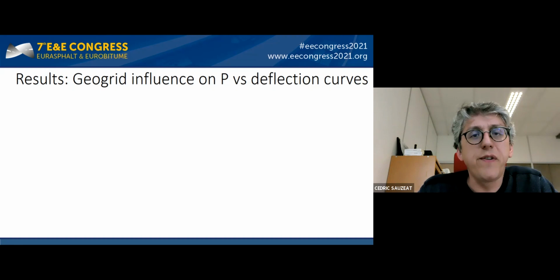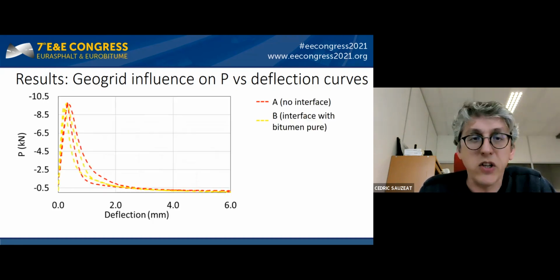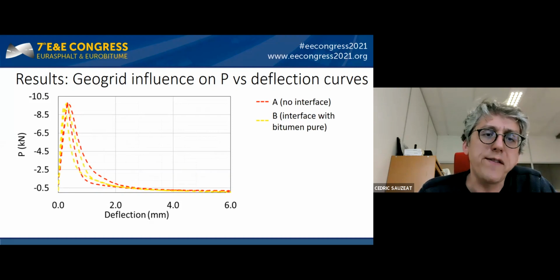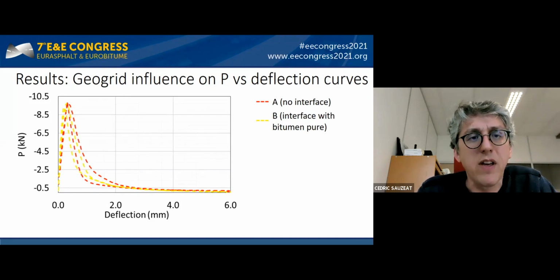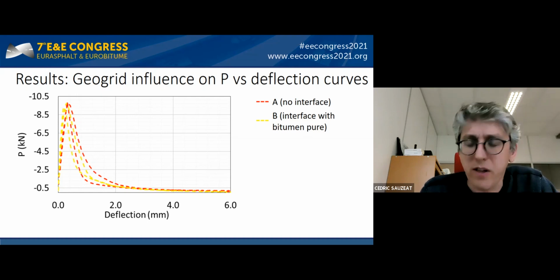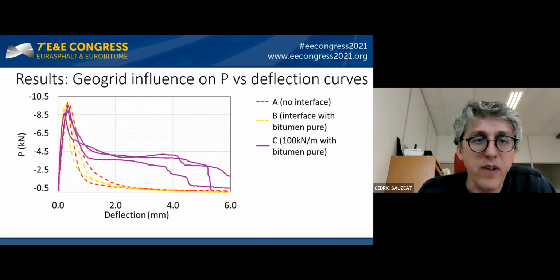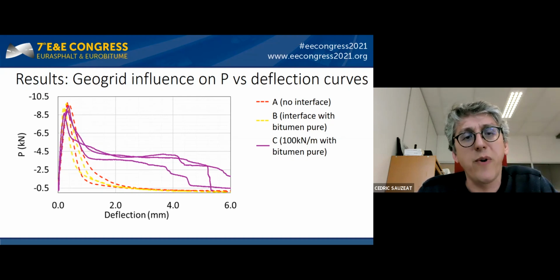First, the geogrid influence on the curve of the load in function of the deflection. Here you have the curve for the unreinforced beam. So you have a peak, and then after the peak, you have a rapid decrease of the load in function of the deflection.